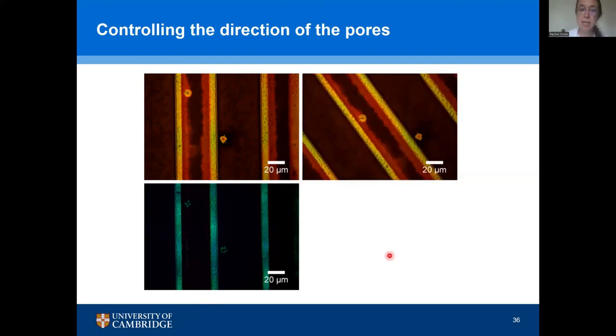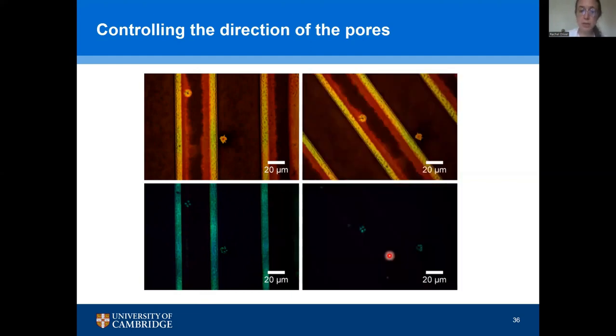And if we rotate our sample, we can actually eliminate the contrast from this porous material, because we can align the direction of the porosity with the direction of the polarized light, and then we have no rotation of the direction of polarization anymore. We still see, however, the Maltese cross, because there the porosity is radial, so there's always some material which is not aligned so well with the polarized light.